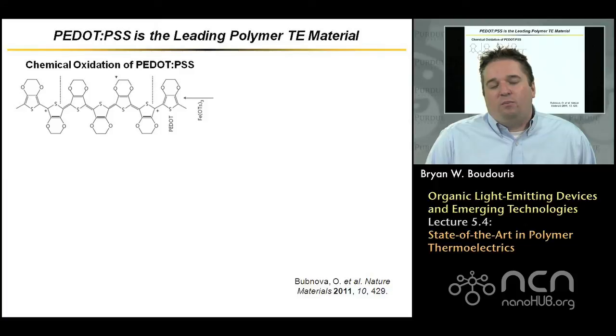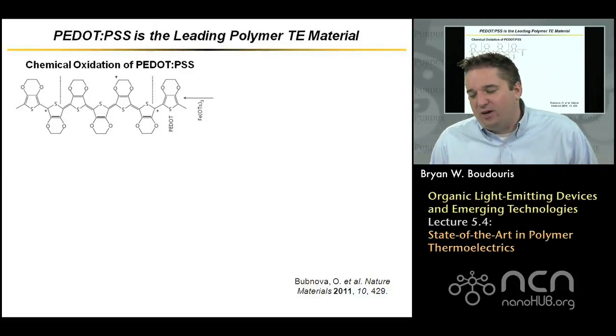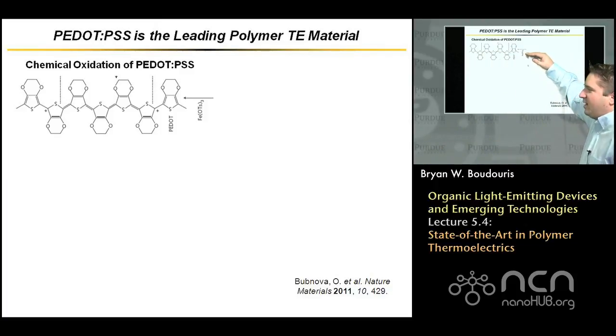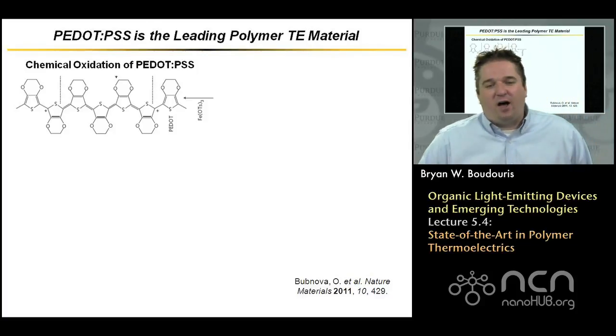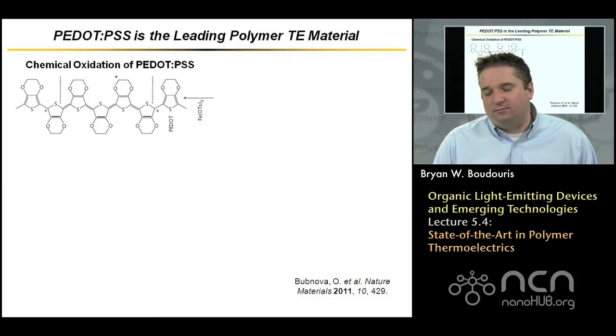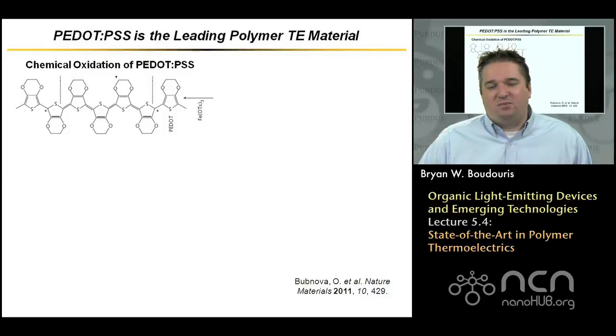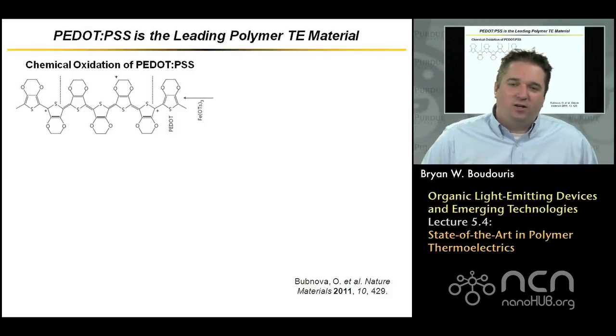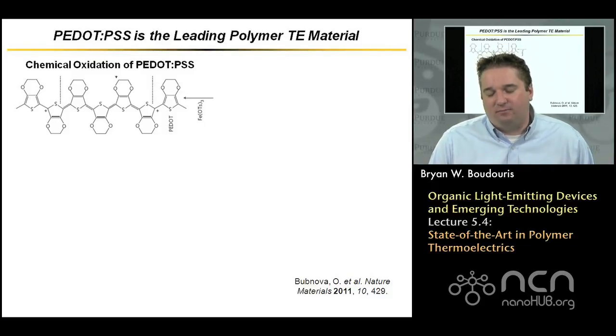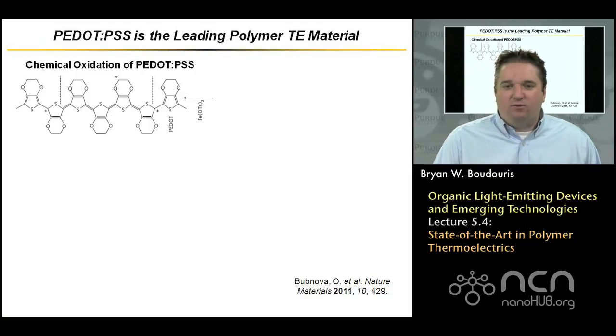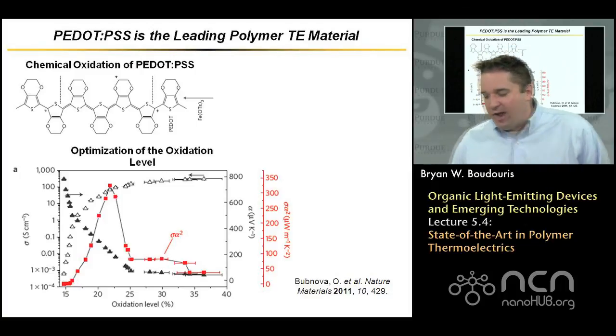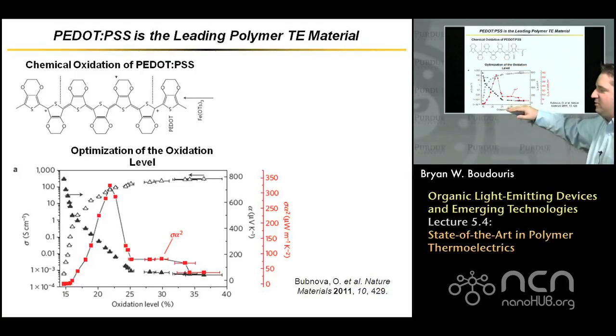Okay? But in a recent result, what people have done is actually oxidize it further. And to do that, they've used an organic compound that's based with an iron atom in the center. Okay? This iron tosylate. And they've used this to oxidize the PEDOT PSS beyond what it is straight out of the bottle. Okay? Now when you do this, you can actually look at how the device performance changes as a function of oxidation level. Okay?